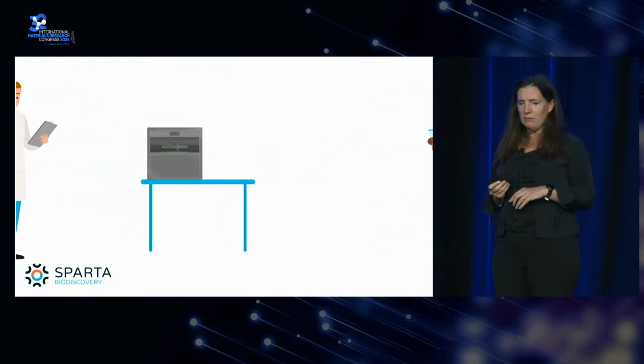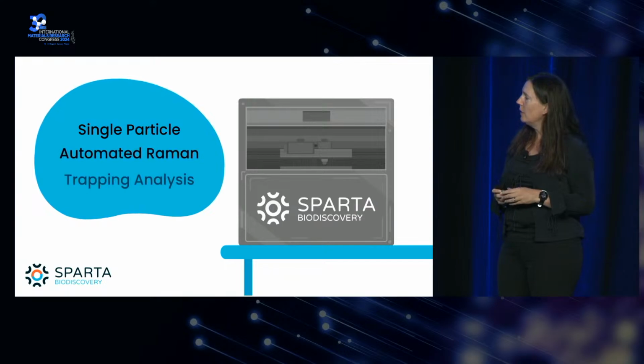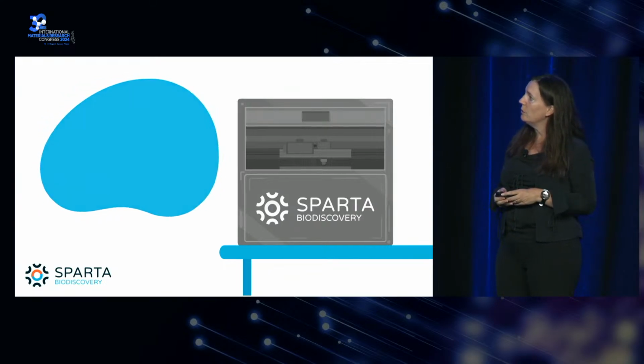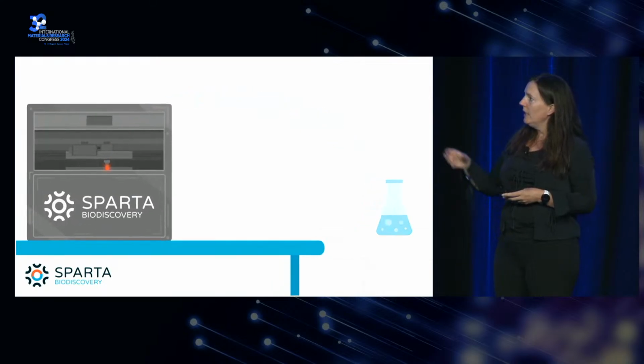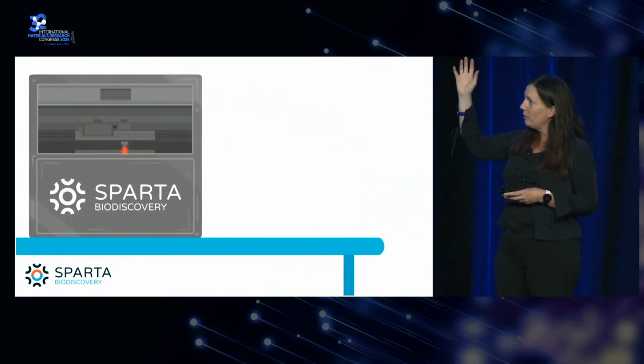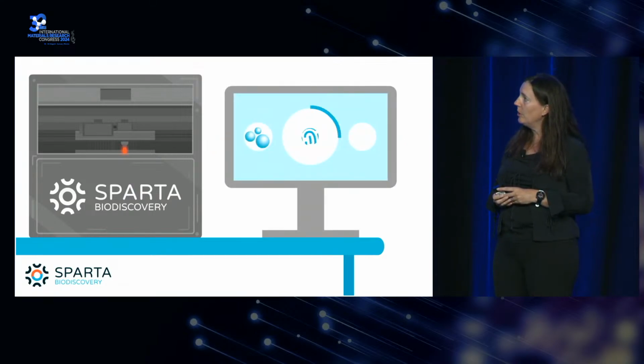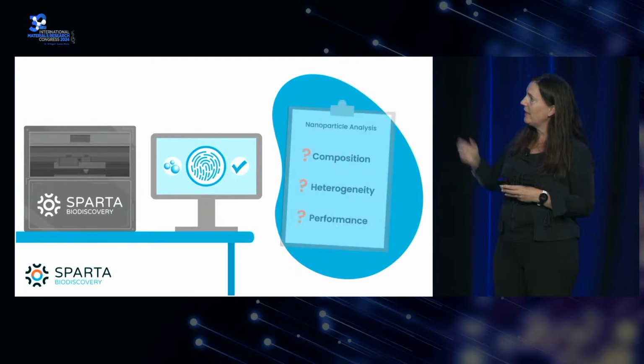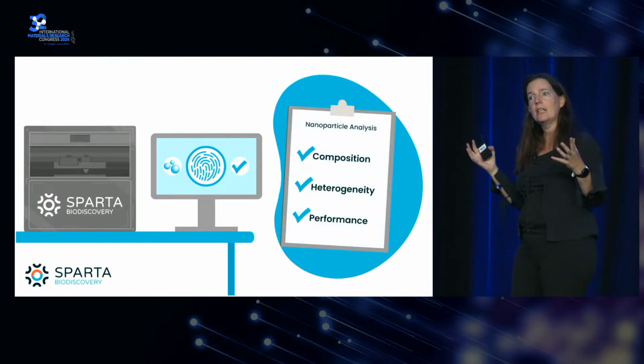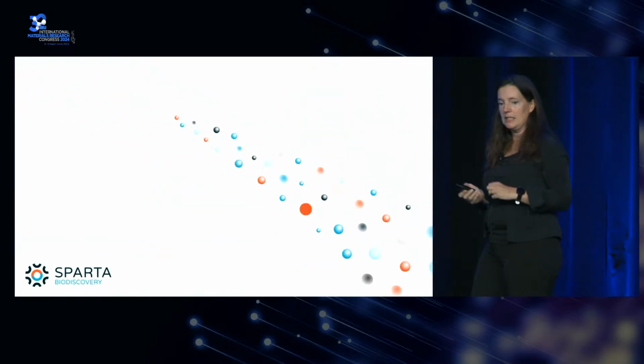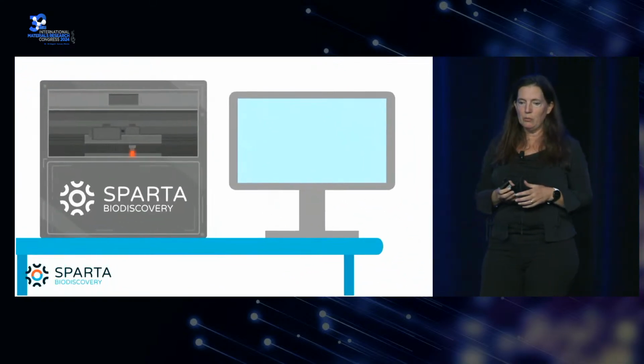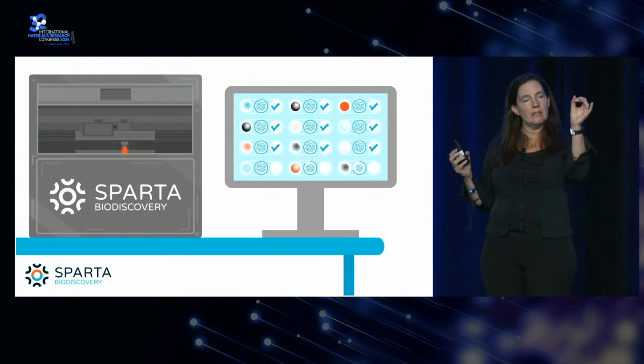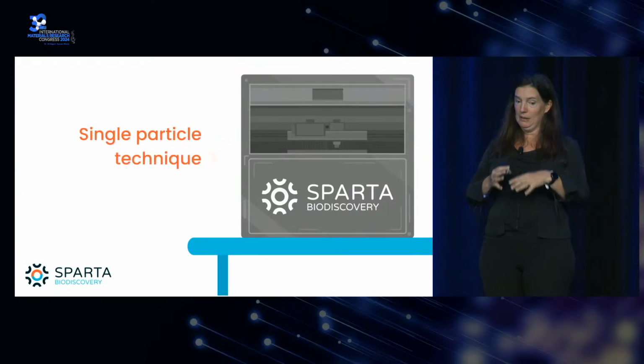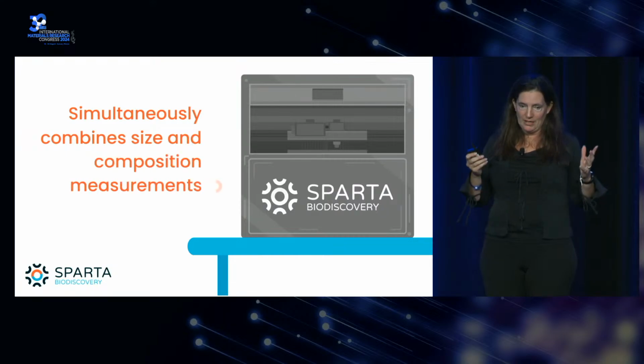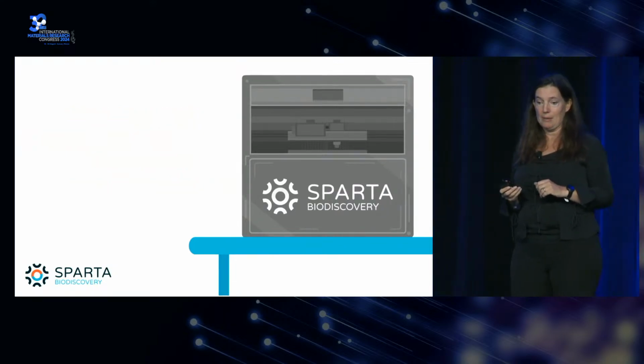And so we developed a technology that's now spun out into this company, SPARTA Biodiscovery, called single particle automated Raman trapping analysis. And what this does is we can trap our nanoparticles from a bulk population of nanoparticles with a laser. We can measure their chemistry with Raman spectroscopy and understand the composition and also the heterogeneity of our nanoparticle systems. And we can look at very complicated mixtures, but study the nanoparticles down at single nanoparticle resolution, all in this automated way. So you can get information about hundreds, if not thousands of particles within your sample.